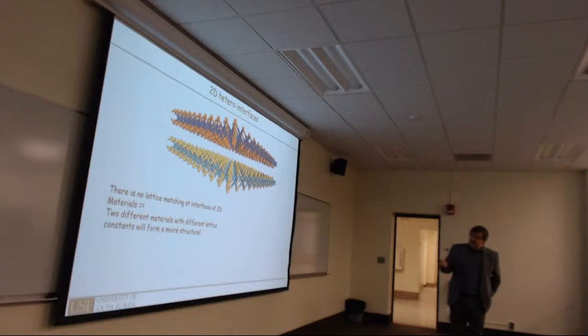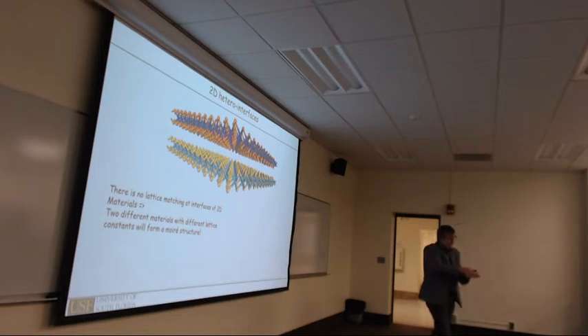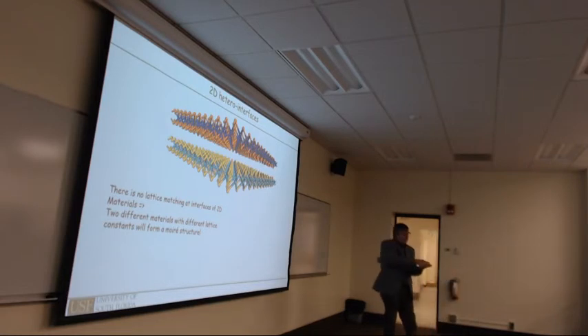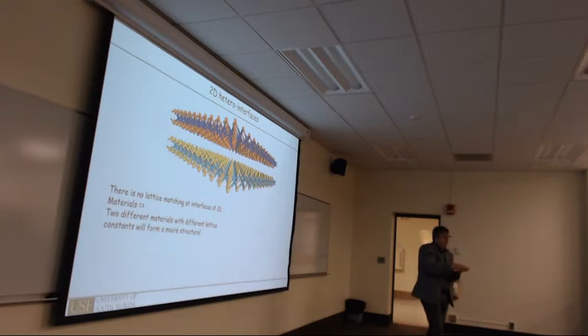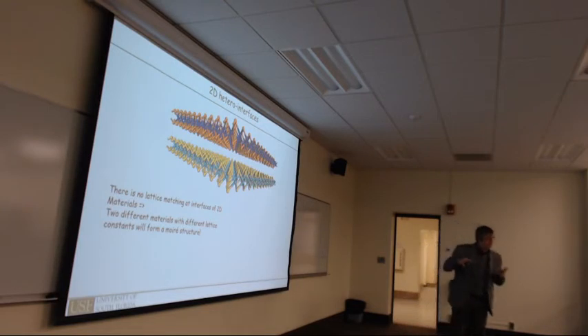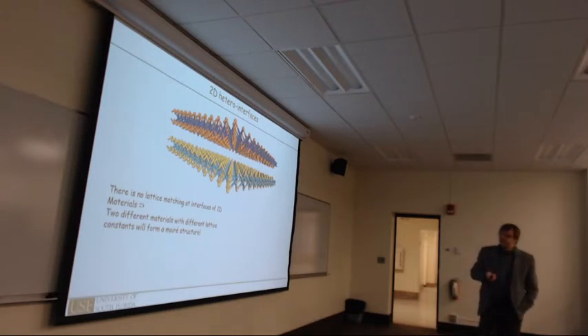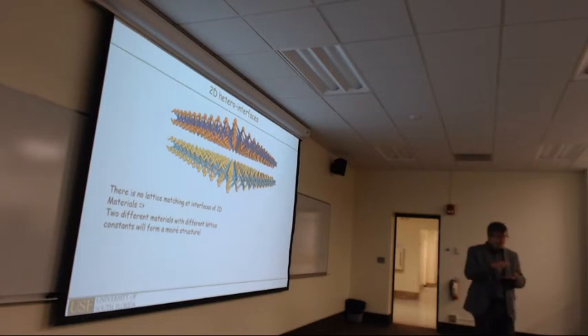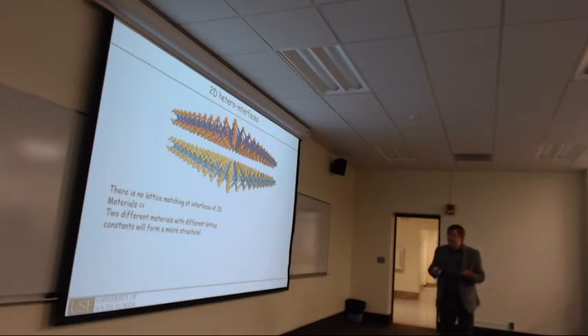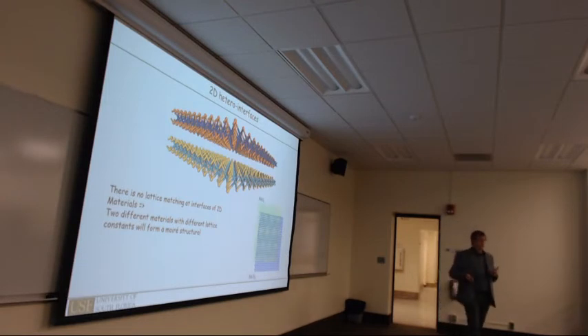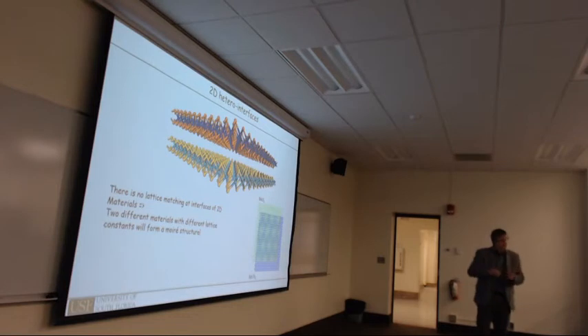Another point we should make is that because there's a van der Waals gap, if you grow one material on top of another, as we've seen before from the LEED, there's no lattice matching between the two materials. They interact very weakly, and therefore every layer more or less maintains its lattice constant. But if you do put two hexagonal layers on top of each other with different lattice constants, let's say here molybdenum ditelluride on a molybdenum disulfide substrate, then they cannot match everywhere, and you get this moiré superstructure.